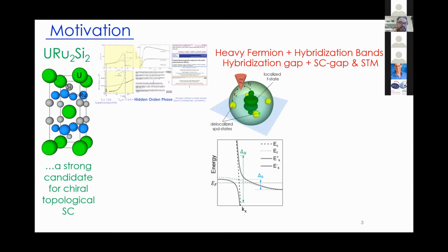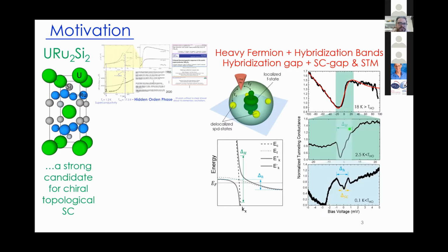In these compounds, the electrons of the localized states hybridize with the conduction electrons, and this hybridization process generates the heavy bands. The strong interactions between the localized and the conduction electrons generated by this hybridization process can be measured using scanning tunneling microscopy. For uranium-ruthenium-2 silicon-2, at temperatures above the hidden order phase, the density of states can be fitted using the well-known Fano function.